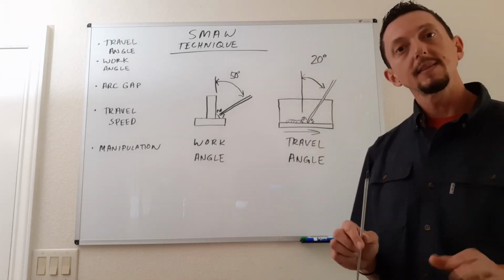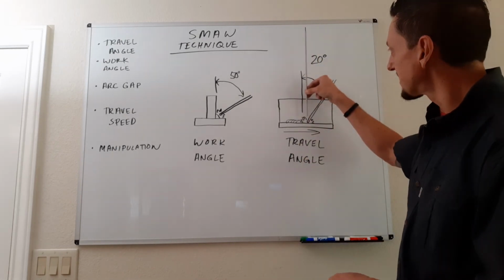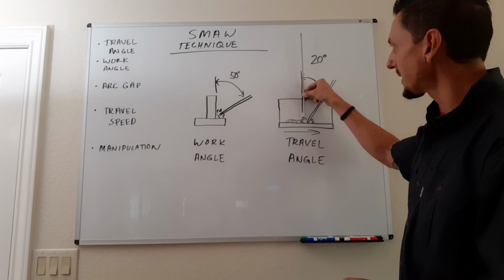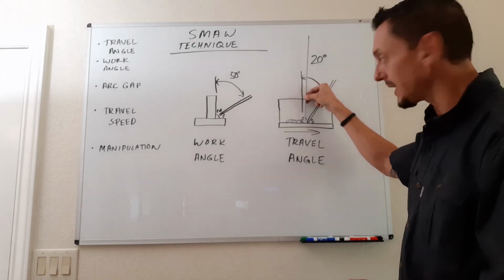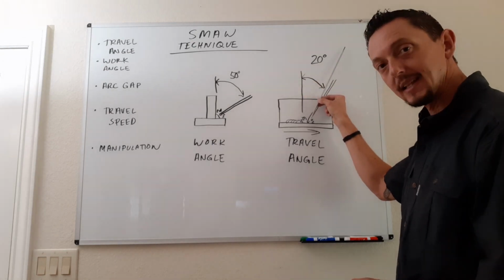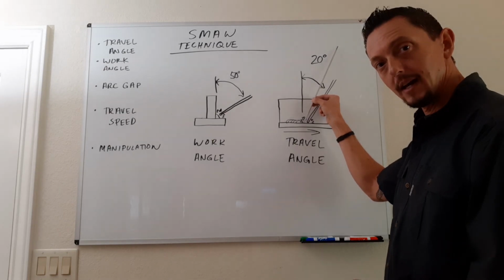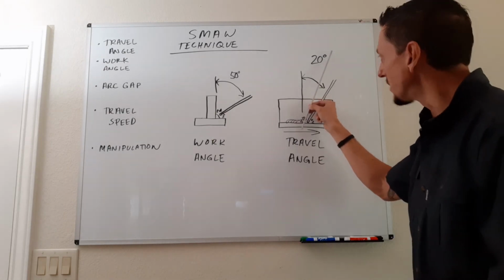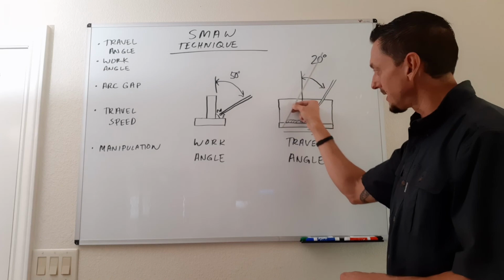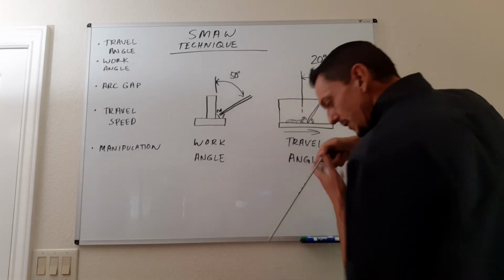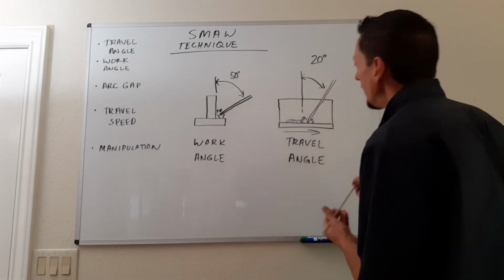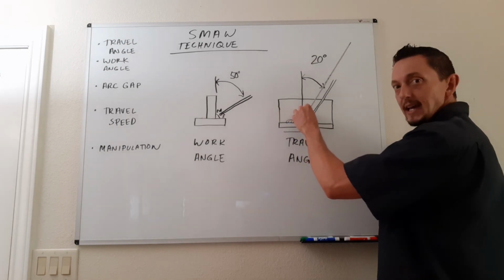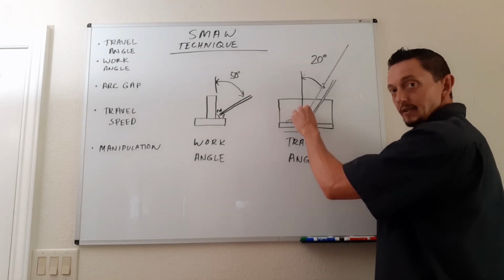All right, so we can see from this diagram that we're not going to use a straight up and down travel angle. We're going to use a slightly angled travel angle. So at about 20 degrees is what we want to hold the electrode at as we're welding along. Okay, so just a slight drag angle is going to give us the best profile to our weld.